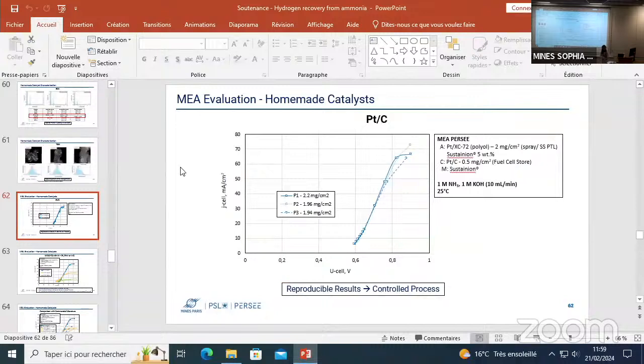And so, if we then really want to focus on the kinetic data, here every time you are showing the raw data, or let's say the uncorrected data, in terms of the potential as a function of the current. In order to really look into the kinetics, have you measured any EIS to extract the high frequency resistance of your device in order to correct for all the IR losses? I'm sorry, I didn't understand. Did I measure what? The high frequency resistance using electrochemical impedance spectroscopy in order to correct for the ohmic losses that you could have. I didn't really measure that.